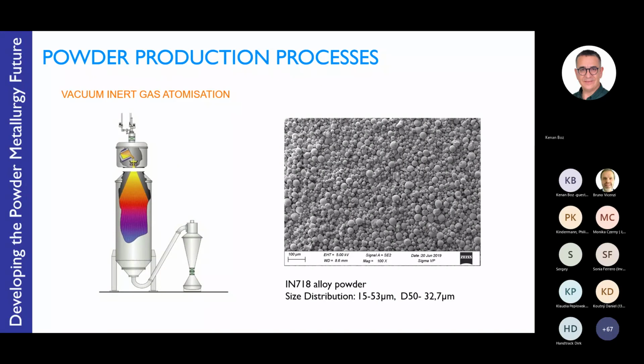Of course, you can't atomize under vacuum, so you have to typically backfill with argon gas. And most of the vacuum inert gas atomizing facilities run with argon atomization, but sometimes nitrogen is also available. And here you can see an example of a superalloy Inconel 718 powder with a size distribution of 15 to 53 microns, and a median size, a D50, of around 32.7 microns.